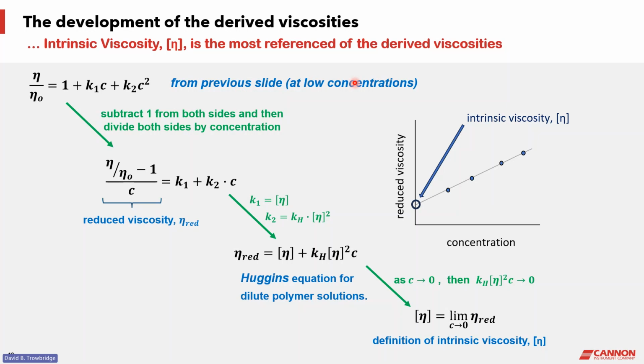So the truncated working equation is here for low concentrations, and we can do some manipulations. We can subtract 1 from each side. So the numerator shows that 1 being subtracted from the relative viscosity here. And then we can divide both sides by concentration. So that puts the concentration on the left underneath the relative viscosity minus 1. And this is an important expression because it represents one of the derived viscosities, the reduced viscosity. And on the right side, the concentration from the first term goes away because of the division that we operated. Also, the concentration goes from squared to just a single power in the second term.